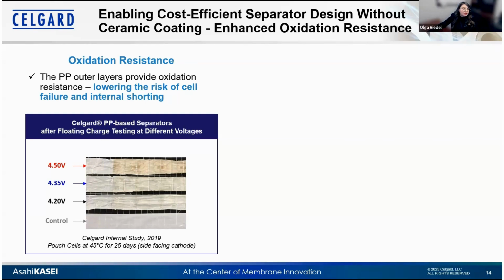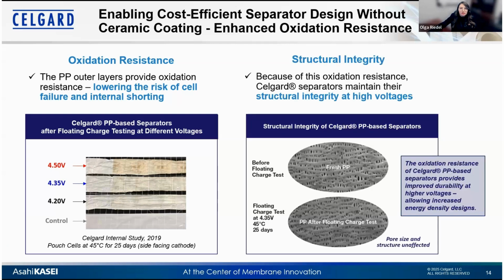So here you see a floating charge test that we performed at 45 degrees C, where we apply a constant voltage of 4.2, 4.35, or 4.5 volt. And we let the voltage float for 25 days at this temperature. After the cell tear down, we observe that the pore structure is unaffected, and we do not see any reduction in film thickness, nor any decline in mechanical strength, which means also that there's no pore closure or pore collapse, and the cell retains its initial resistance. With that, our Celgard separators provide high durability at high voltages.